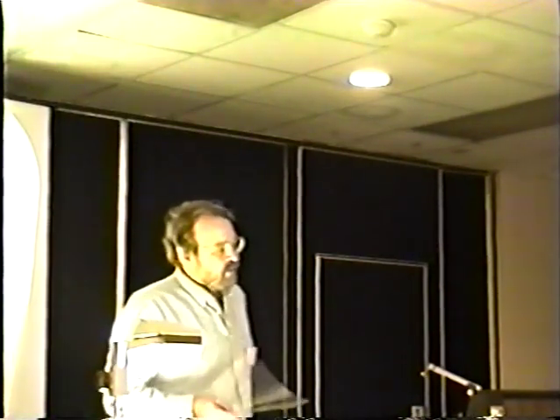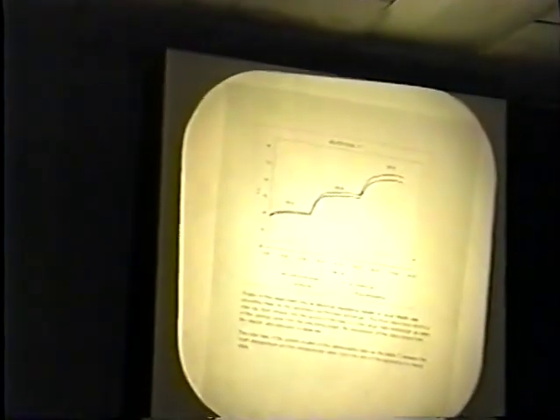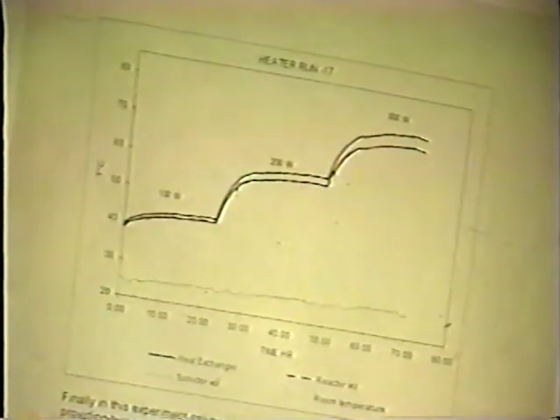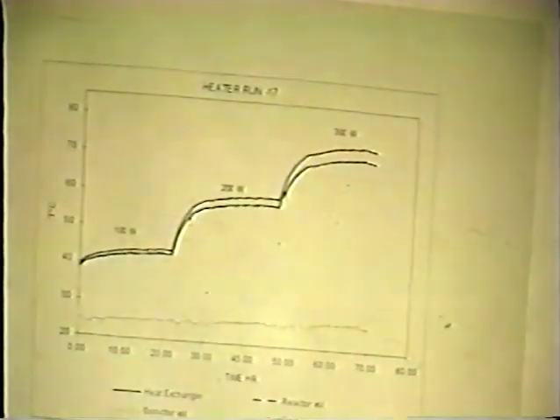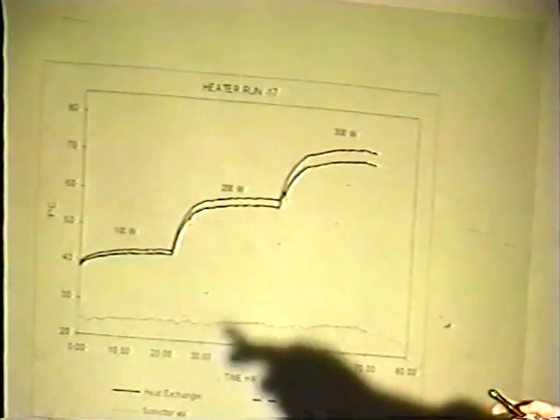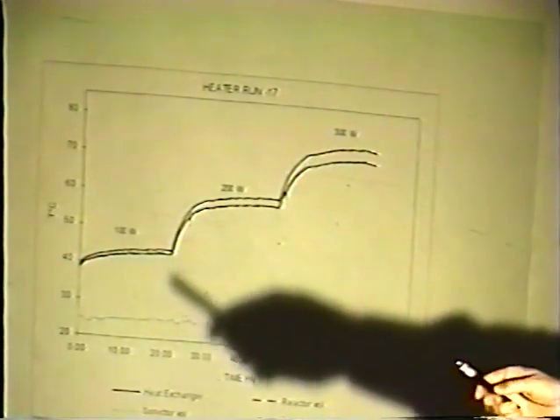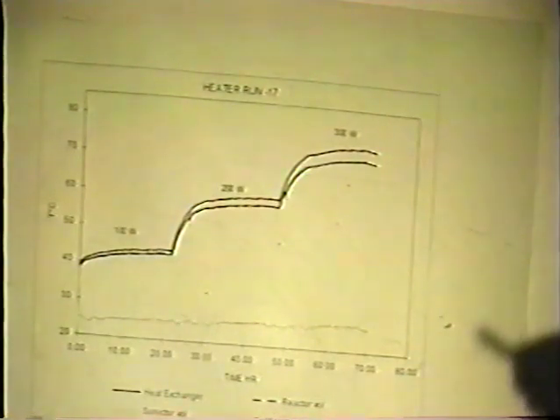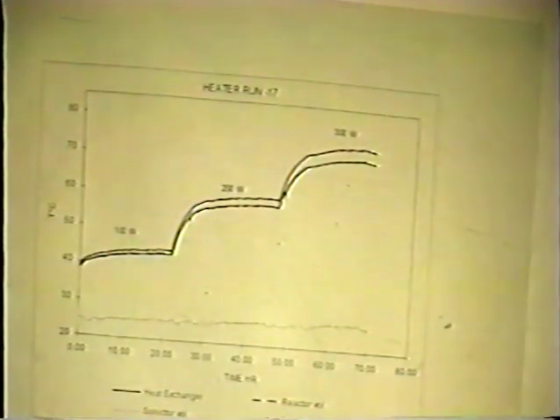But to give you an idea, all of our experiments are run as a calorimetric experiment, and we have an internal joule heater calibration in the system. And so what we do is steady state calorimetry as well as mass flow calorimetry, although we rely on the steady state calorimetry as the method. And this is a plot of the internal joule heater calibrations that we see. So when we put 100 watts in the system, we see it rise up to a steady state and stay there. And when we put 200 watts in, we see these lines come up and find a nice steady state. And at 300 watts, we're pretty close.